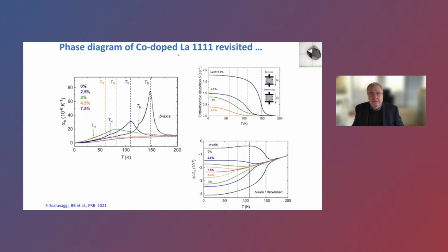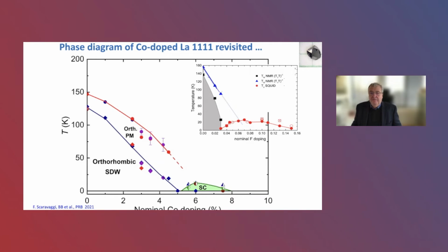So of course, what we can do now is we can use more sophisticated experimental techniques to study the phase diagram. And some results are published in this paper, for example, measurements of the thermal expansion, where we use dilatometry to study both the structural phase transition, so that means the nematic phase transition, and the magnetic transition. You can even see it in the lattice. So you're just measuring the size of the crystal. You can also measure the magnetic phase transition.